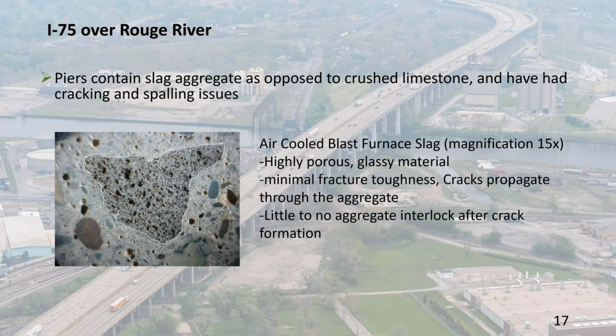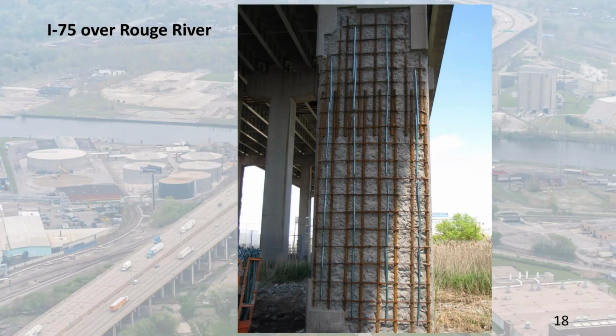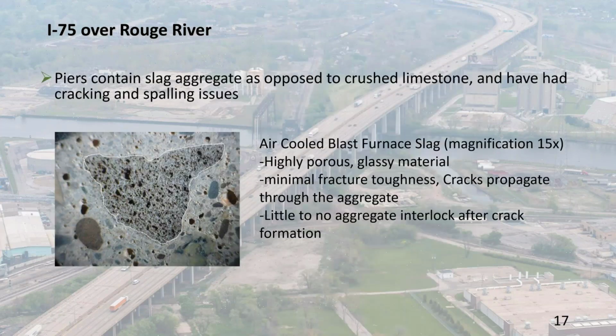This is Steve Kahl, and one of the reasons why we wanted to use carbon fiber as a passive external reinforcement to bolster the repairs is that the slag aggregate is not good for longevity in terms of crack resistance. It is a highly porous, glassy material, as you can see from the picture there, magnified 15 times, and I drew a little outline around it to pinpoint it or separate it from the surrounding paste, but it's obviously apparent.